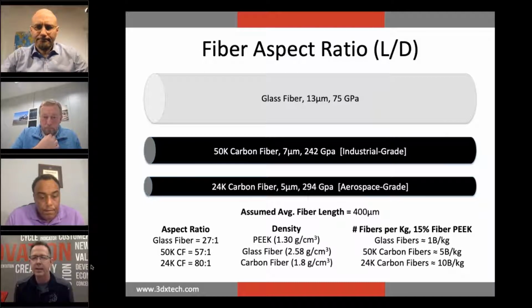What the slide on the lower right shows is that, given everything equal, which never is, but say we had to pick a fiber length to do the math, with glass fiber in that composite, you're going to end up with about 1 billion fibers per kg. With the 50K, you're going to end up around 5, and with the 24K, you're going to end up around 10 billion fibers in that 1 kg of material. And so if you end up with twice as many fibers and each one of them is 10 or 15% stiffer, you can see that the selection of the carbon fiber really matters. And so with the term carbon fiber, not all fibers are equal. And so we do a lot of work with the different materials to make sure we're selecting the appropriate material for the appropriate end-use application.